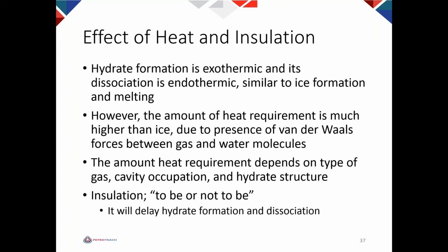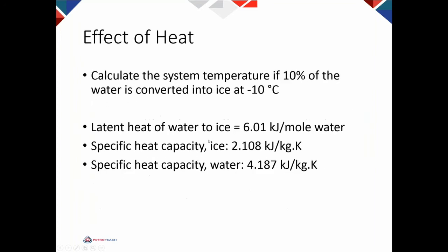You need to remember, if you do insulation, you delay hydrate formation, but at the same time, you delay hydrate dissociation. So you need to be aware of this. If you have insulation, it takes more time to block the pipeline, but it is more difficult to melt by depressurization. Obviously, for a gas pipeline, we don't use insulation because the Joule-Thomson effect can reduce the pressure and the temperature quite significantly. There are some examples here.